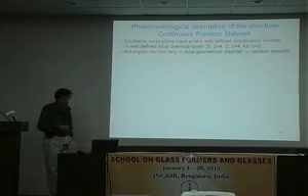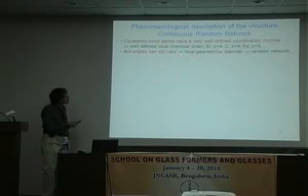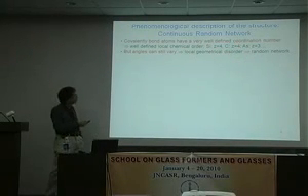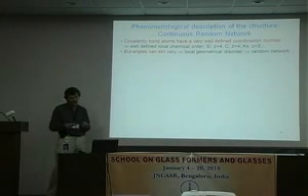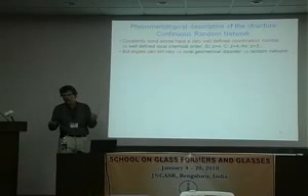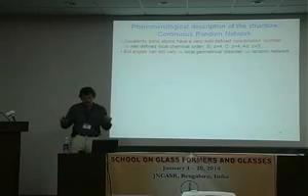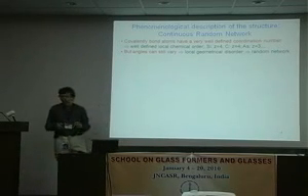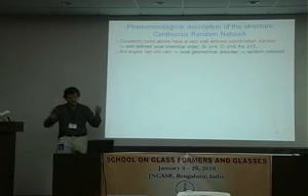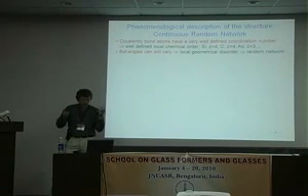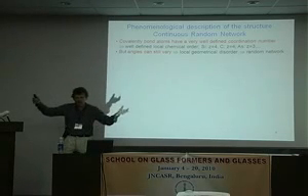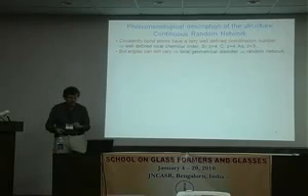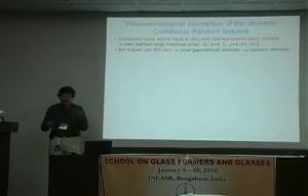70 years old, I think. So I forgot, it's Zachariasen who proposed this for the first time. And the physical idea is very simple. For covalently bonded atoms, like silica, for example, silicon and oxygen, you have a very well-defined coordination number. That is, the silicon, a priori, wants to have 4 neighbors. The oxygen wants to have 2 neighbors. A carbon atom wants to have 4 neighbors, etc.